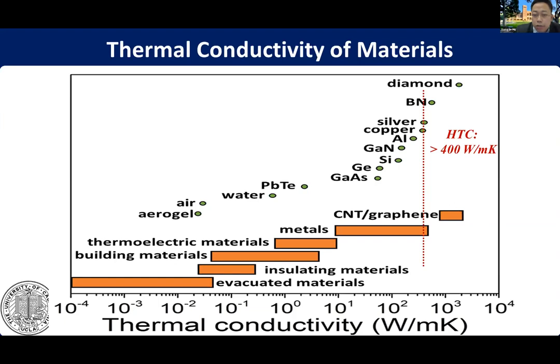And the other option is carbon-based nanomaterials, such as carbon nanotubes and graphite. They have attractive high thermal conductivity for individual devices. The challenge is when you assemble them together, there's degraded thermal conductivity due to ambient scattering, and also the intrinsic anisotropy due to van der Waals bonding leads to low thermal conductivity and mechanical property in the cross-plane direction for graphite.